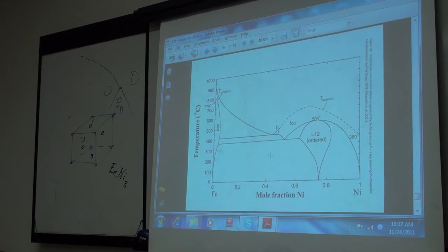Here you have an order-disorder transformation that is always first order. You never have a second order phase. You always pass by a two-phase region. Even if you take the pure 75% and you heat it, it transforms; it is not completely disordered when you reach 75%. So when you cross here, there's a discontinuity in the heat as the thing becomes.